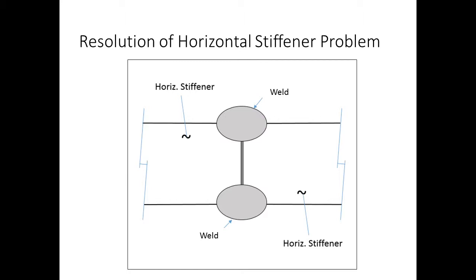In a fatigue situation, as a result of the welding process, we don't get a complete penetration weld, and we have this piece in here where the pieces of bar stock aren't completely welded together, and this little area acts as a crack starter in a fatigue loading environment.